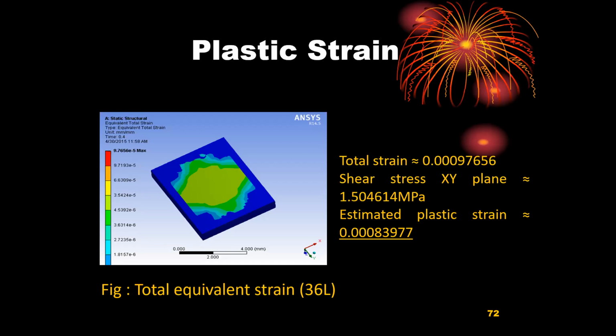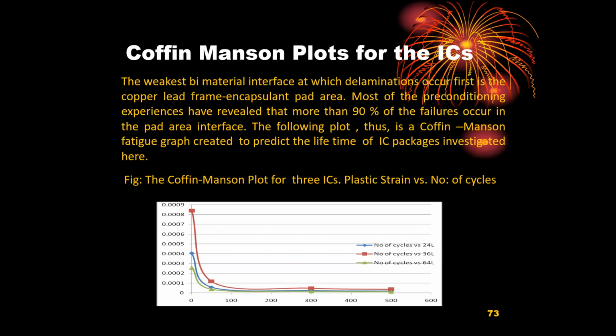Normally we assume that cell phones are very rarely switched off, but laptops and desktops are switched off more often. So we had to take such things into consideration. And the total strain and then the plastic strain were all calculated. And we had to go back and find the weakest bimaterial interface at which delaminations occur first, and where they occur we had to check, and it was normally in the copper lead frame encapsulant pad area.